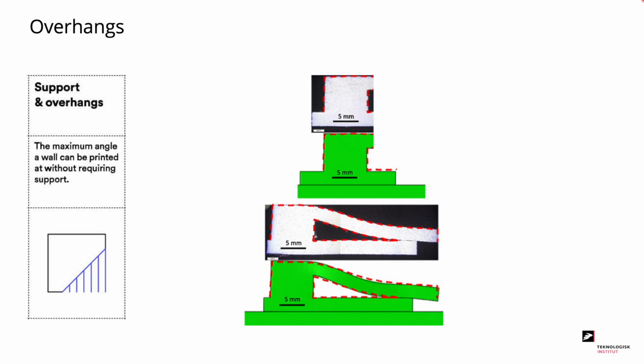We use simulations to predict the deformation during the sintering step. The green pictures are results of a simulation, and the gray pictures are a result of actual sintering parts. In the top you can see a small overhang with no deformation, and in the bottom you can see a large overhang which was straight before sintering, which collapses completely during the sintering stage.